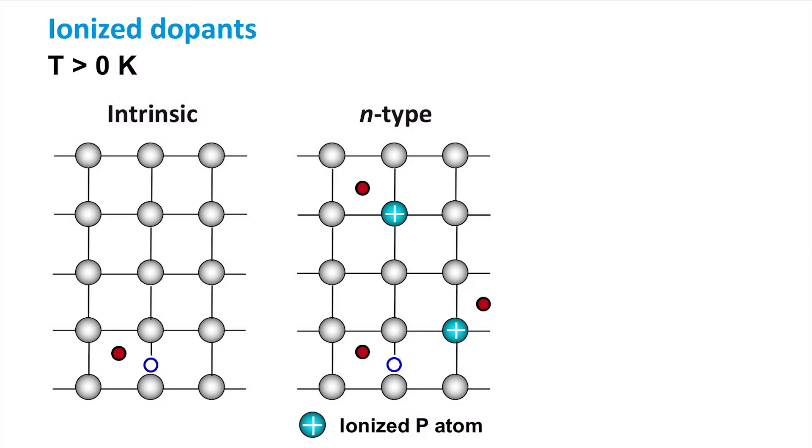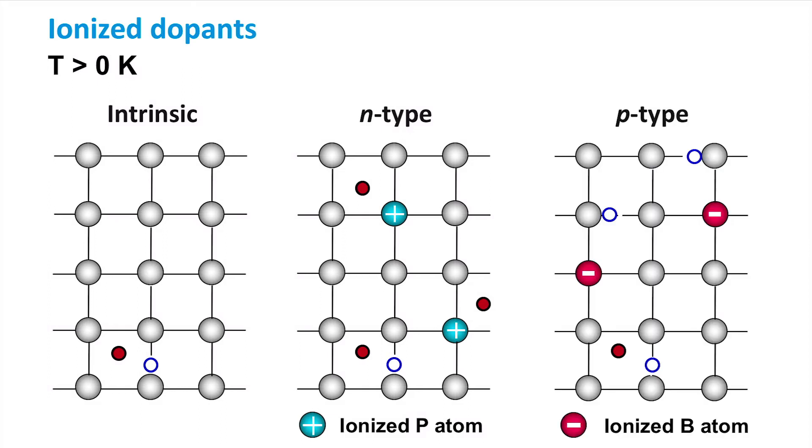For this reason, phosphorus is also called a donor. If this mobile electron leaves the phosphorus atom, the phosphorus atom becomes positively charged. This is because it has more protons than electrons now. In p-type materials, electrons can be readily accepted by boron atoms to fill the holes and complete the covalent bond with silicon atom. We call dopants like boron acceptors. The boron atom becomes negatively charged since it now has accepted an extra electron. We say that boron atoms are negatively ionized.